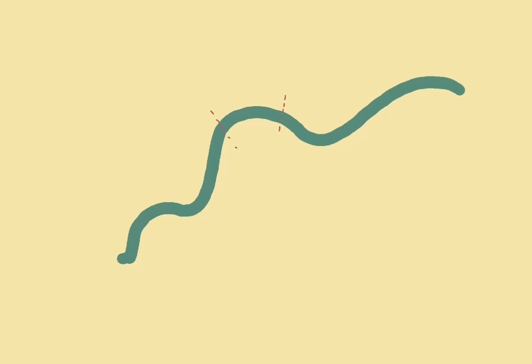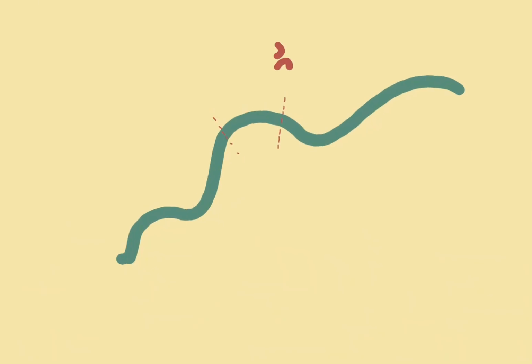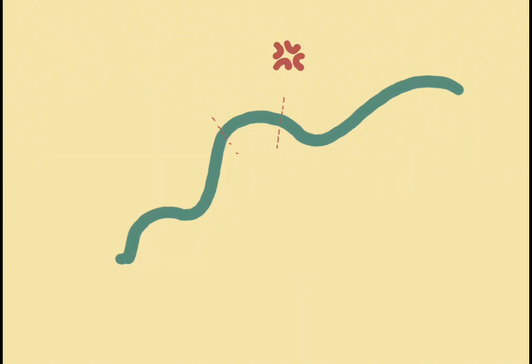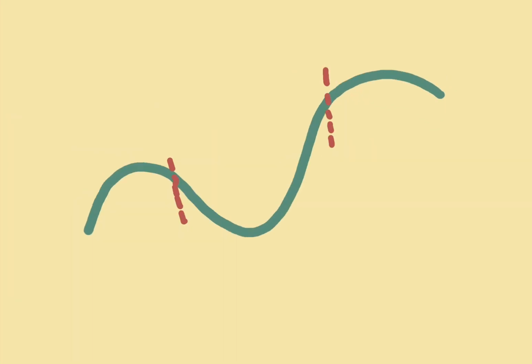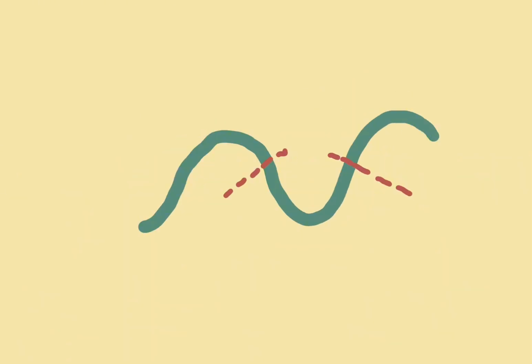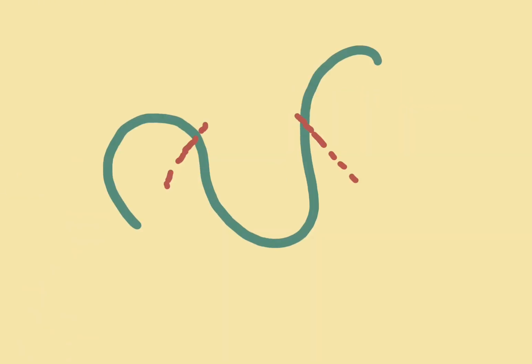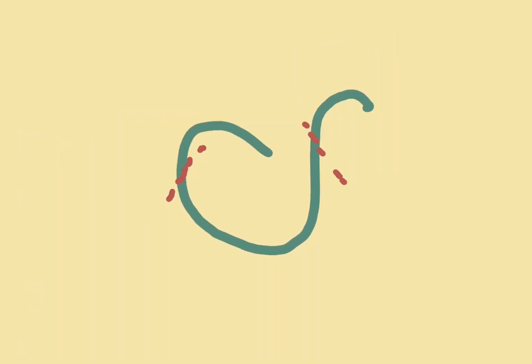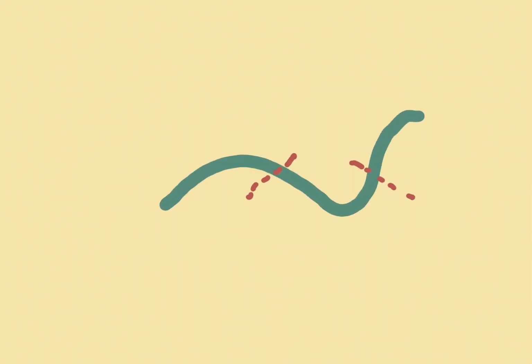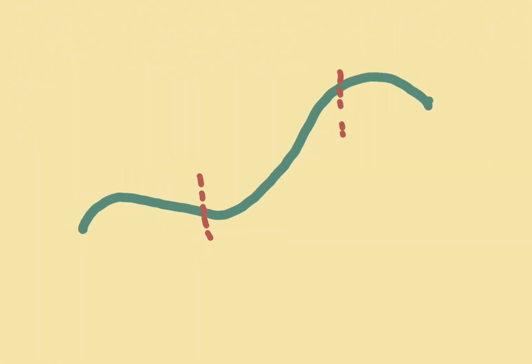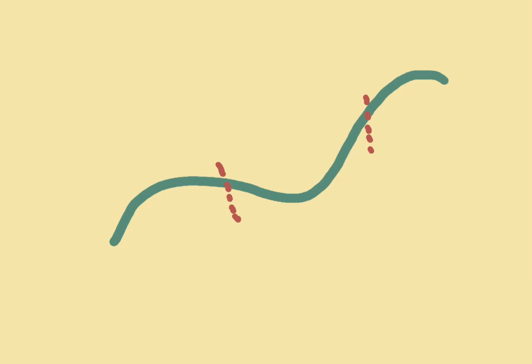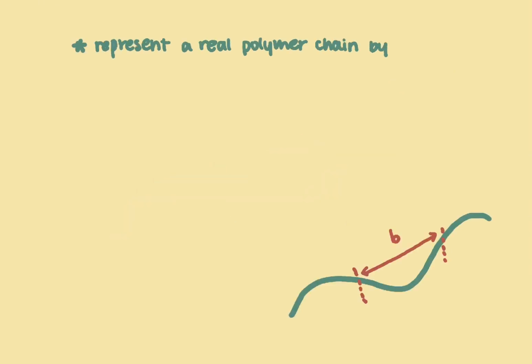We can imagine trying to bend a relatively rigid coil. If the two hands hold up too close together, the coil is not too likely to bend. This mimics the failure of the freely jointed model in polymer behavior, because the coil is not freely rotated. The idea behind Kuhn segment length is to separate the polymer into long enough segments so that the segment can represent the length of an equivalent hypothetical segment that behaves like a freely jointed chain. In other words, it is as if the polymer were made up of straight, non-flexible rods of length B connected by freely jointed joints.